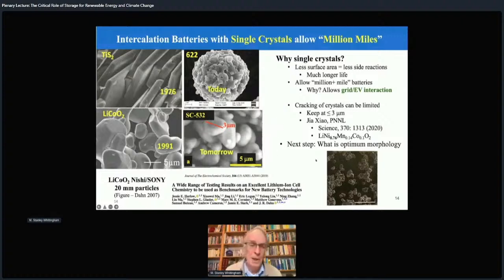So what we're doing is looking at what is the optimum morphology of these materials. You see, this is really the layered compounds, which all these are. The diffusion is into the edges of these crystals, not through the flat plane. So this is not the ideal morphology. So we want to find out what the ideal morphology is. And these are some of Jay's single crystals that she used. And this is now 76% nickel. So high nickel materials. But the other option is to go away from these oxides altogether and work on phosphates.